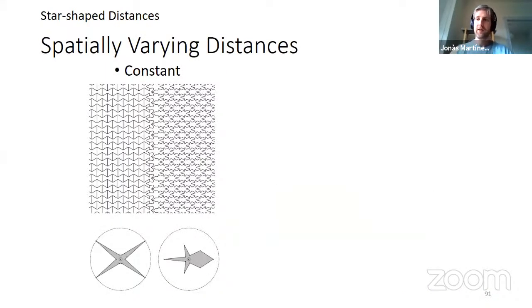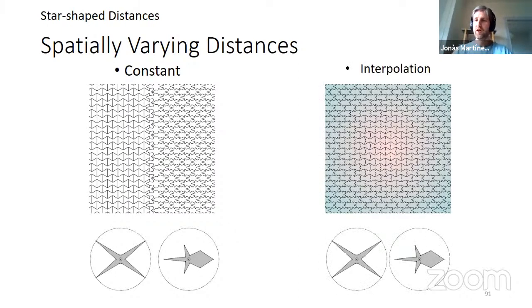And again, this is also the main point of this work. You can transition between different distances by simply changing the distance in one region of the space and the distance in another region of the space. You can do that either constantly, by doing a hard transition, or for instance here, guided by some field. And you can do it because, as you can see, when you do linear interpolation of two star-shaped sets, this leads to another star-shaped set.